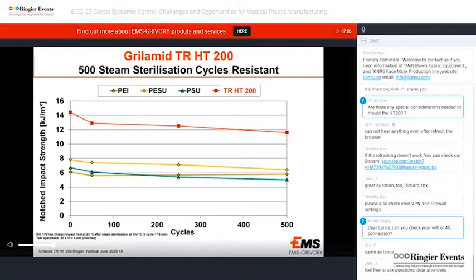Here we look at the steam sterilization resistance in more detail by comparing the notched impact strength of Grilamid TR HT 200 against PEI, PESU, and polysulfone, materials currently being used for repeated steam sterilization use. The steam sterilization process used for this was 134 degrees for 18 minutes with a 90-minute cool down period before the next cycle. The first obvious point is that Grilamid TR HT 200 has a notched impact twice that of the other products, sitting around 14 kilojoules per meter squared, giving it exceptional toughness.